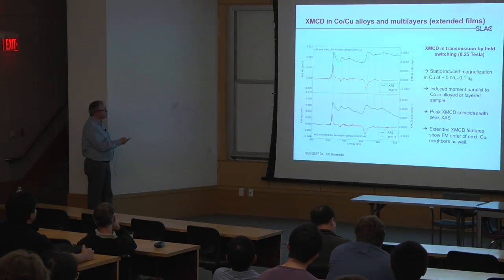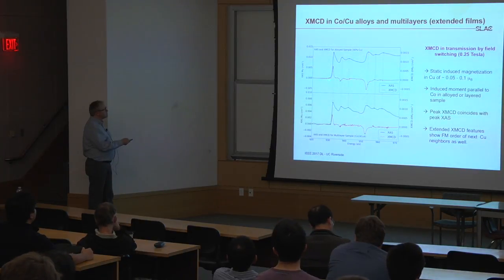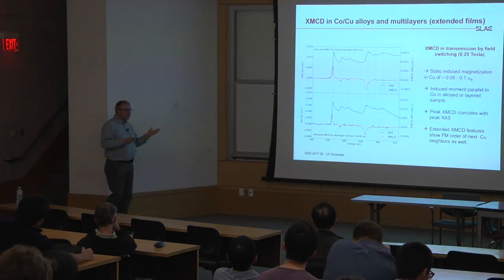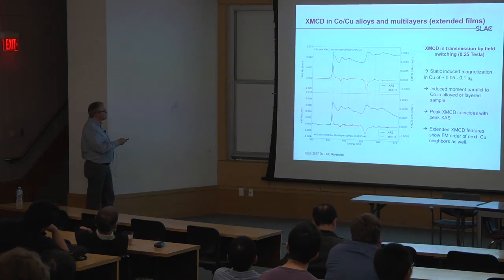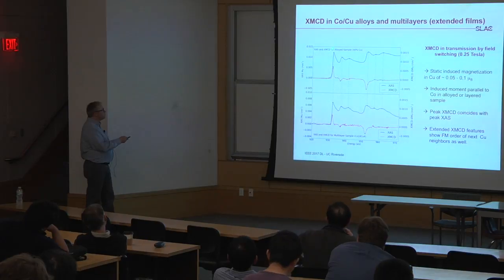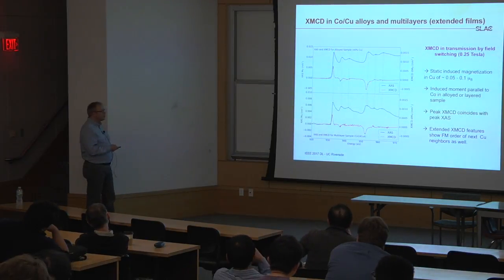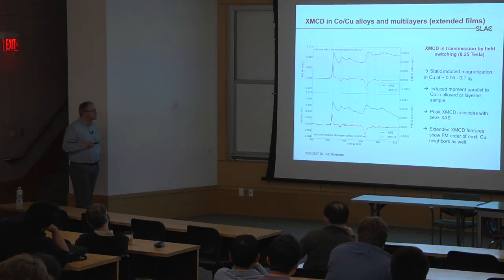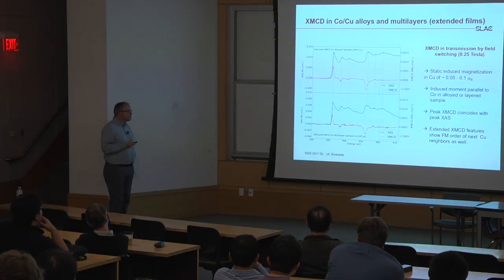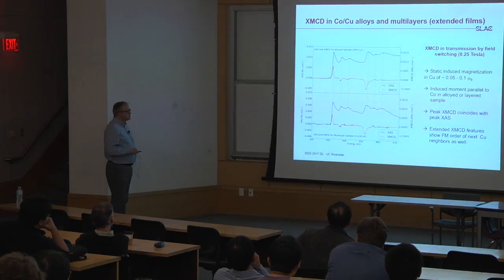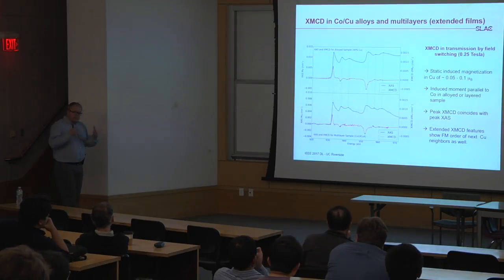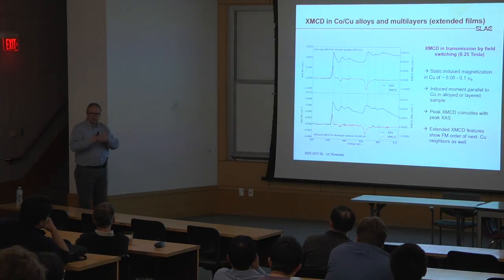So this is the X-ray absorption spectrum, the blue line, of copper with L3 and L2. And this is the difference, the red is the XMCD spectrum between the two magnetizations. And there's a very clear difference. It's about 1% difference between the two spectra, which points up in one direction for the L3 and down for the L2. And that's exactly the signature of an XMCD effect. And we can estimate that the static magnetization alone is probably about 1/10 of a Bohr magneton. And that's just induced by being in contact with each other.